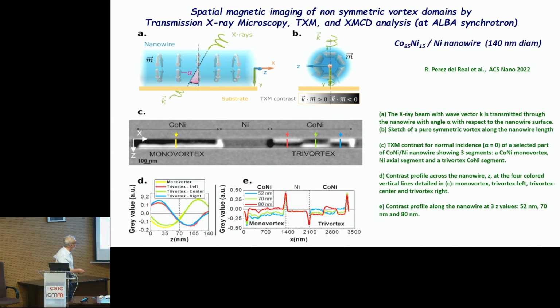So particularly Rafa was involved in this study with a new technique, transmission X-ray microscopy, also in the ALBA synchrotron. You see this is an image of the nanowire. With this technique, it is possible to determine very clearly the distribution of magnetic moments, not only along the length of the nanowire, but also in the radial direction. So again, it is possible to determine the distribution of magnetic moments inside the nanowire.